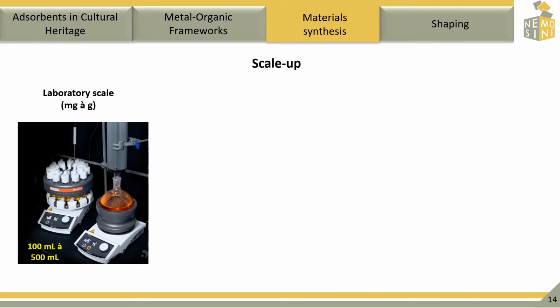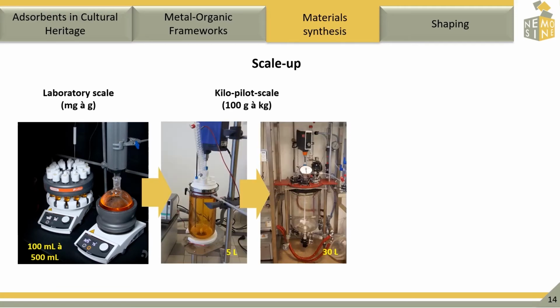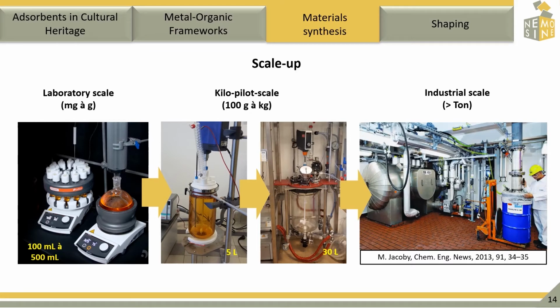In our lab, we are able to do this synthesis method in milligram or in gram quantity, but we are also able to do this synthesis in pilot scale reactors where more than 100 grams or even kilograms can be obtained. With the vital information that we can have with this type of synthesis in the pilot scale production, we can evaluate the feasibility of this process in an industrial scale, meaning the tonnage scale. Thus, we see that the atmospheric pressure synthesis is relevant in order to produce MOFs that can be used in large-scale applications. So in the project NEMOSINE, we aim at finding a currently good performant MOF that can be synthesized with this procedure.